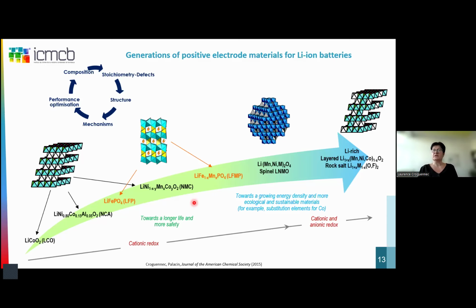Now, in order to answer more and more demanding applications in energy, we are also moving to other chemistries, such as lithium-rich layered oxides, rock salt type structures, and high voltage spinel. And in that case, for the lithium-rich layered oxides, we are even jumping in structures and compositions, where we have cationic redox and, in addition, anionic redox.